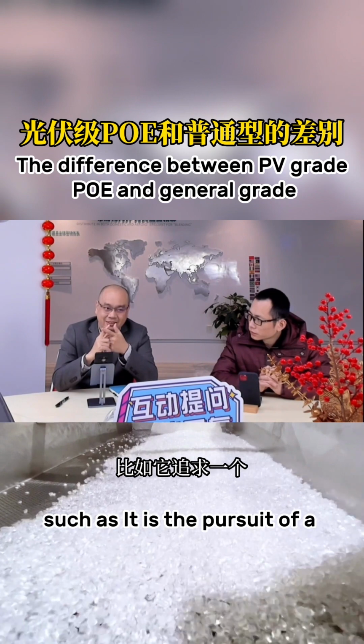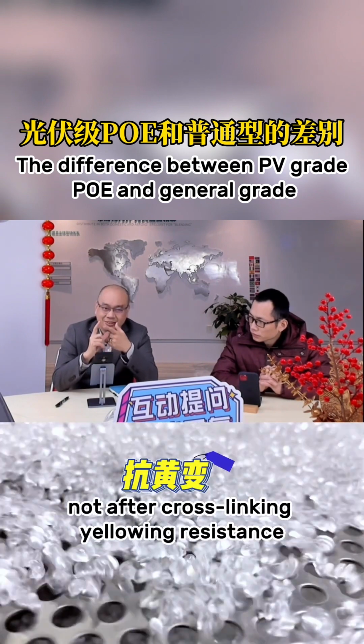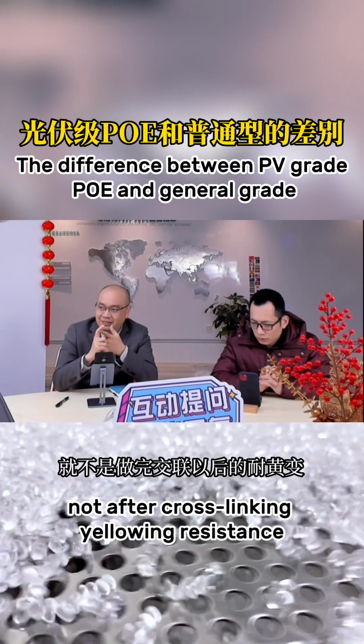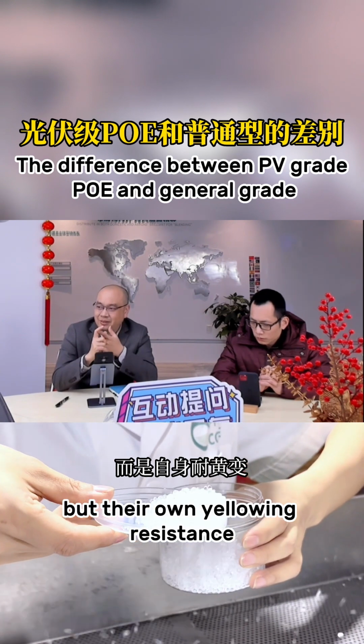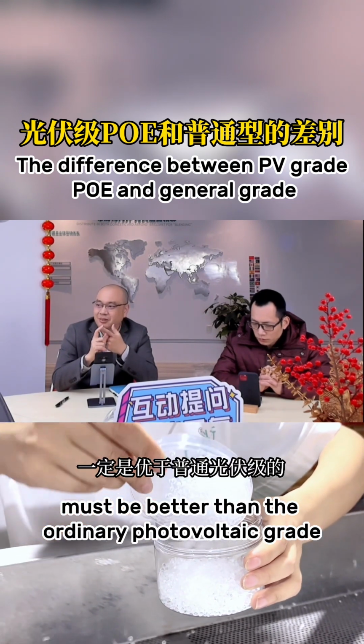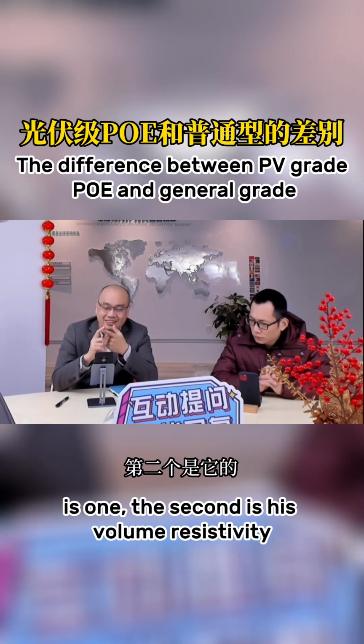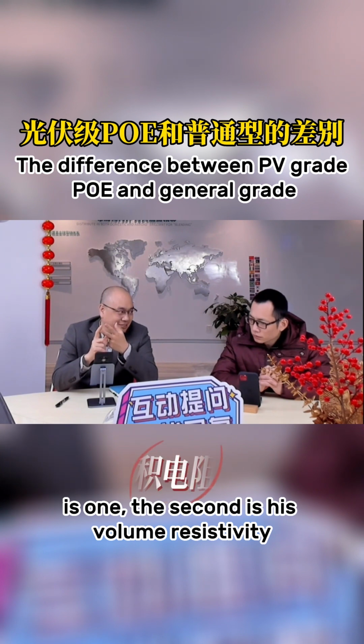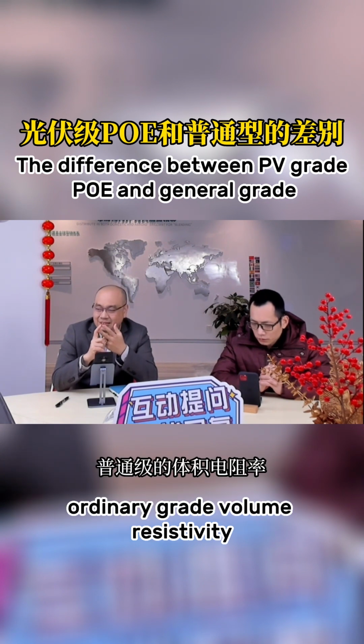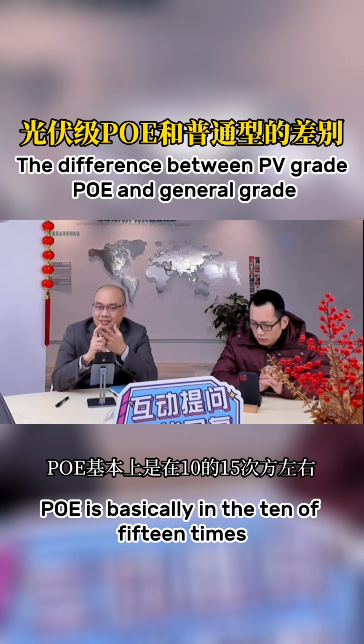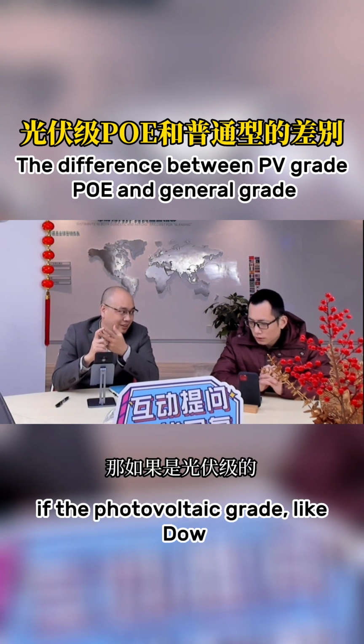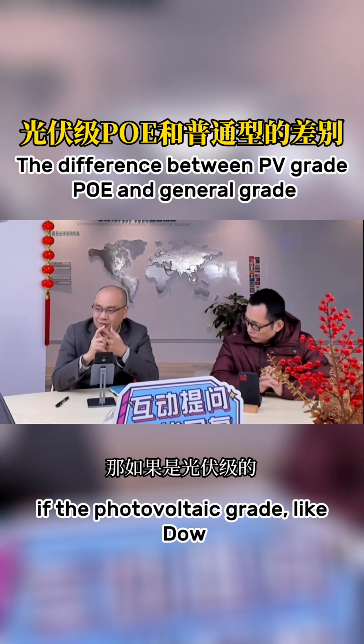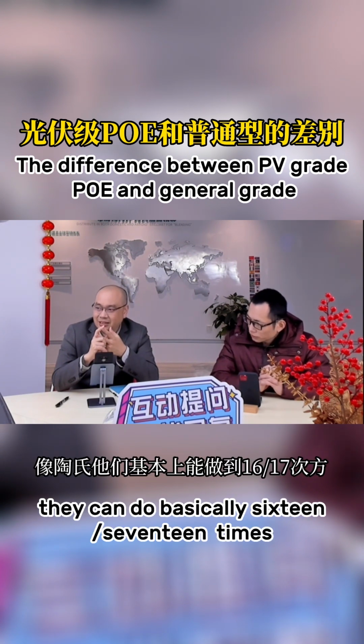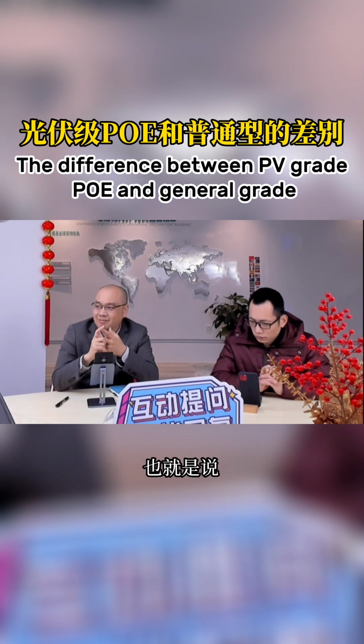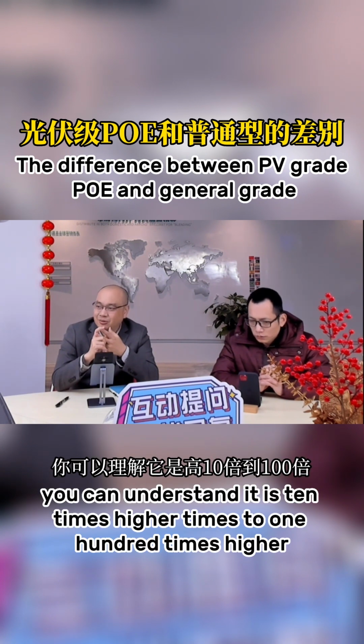the pursuit of yellowing resistance, not yellowing resistance after cross-linking, but their own yellowing resistance must be better than the ordinary photovoltaic grade. That is one. The second is volume resistivity. Ordinary grade POE volume resistivity is basically around 10 to the 15th. If it is photovoltaic grade, like Dow, they can basically do 10 to the 16th, 17th. That is, you can understand it as 10 times higher to 100 times higher.